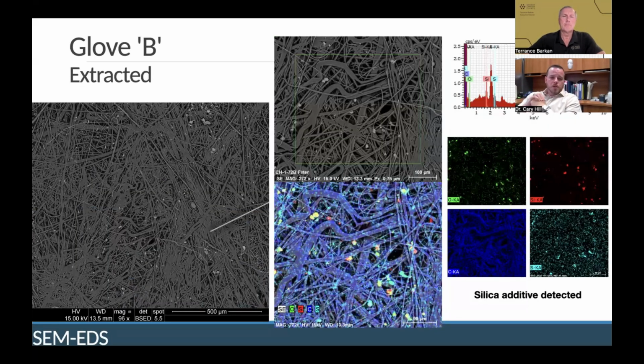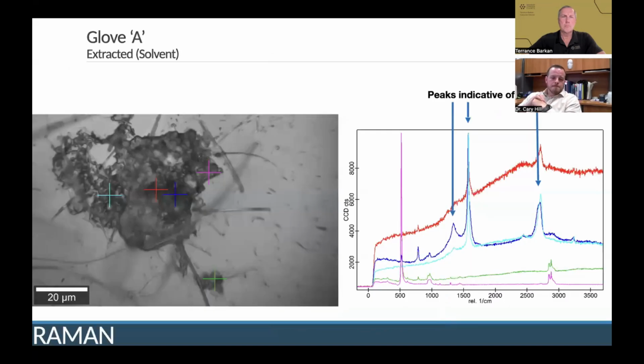And we performed our extraction, dissolved the fibers, and then the release material was analyzed. And again, we just found a lot of silica content. That was kind of the main takeaway. The steel fibers were also removed before this analysis. They came out in a big steel wool looking mass, and so we just pulled those out to look at the particulate additives. Did not find any evidence of graphenic content, found a lot of silica.